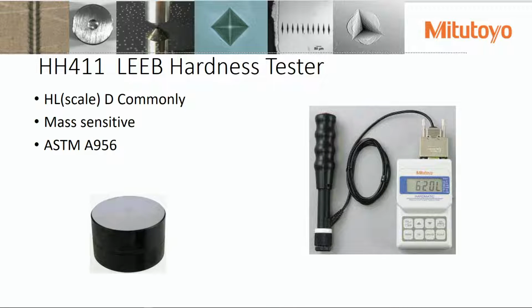Okay, we have the HH411, which is a rebound tester or a Leeb hardness tester. One of the great things about this is that there's an ASTM and ISO standard for these materials. There are several different probes that you can use on this, but basically it shoots a little carbide ball against the part, and we measure the difference in the velocity from before it impacted the part to after it impacted the part, and that gives us a hardness number.